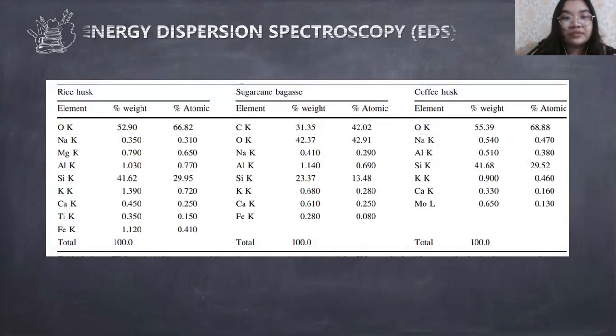Next table is about showing the bioprocess of silica oxide particle synthesis, and we can see the amount of silica and oxygen in each agro-industrial waste. For rice husk, it has 41.62% silica and 52.90% oxygen, 23.37% silica and 42.37% oxygen for sugarcane bagasse, and lastly 41.68% silica and 55.39% oxygen for coffee husk. It also indicated other elements with lower percentages, like sodium, magnesium, aluminum, potassium, and calcium.